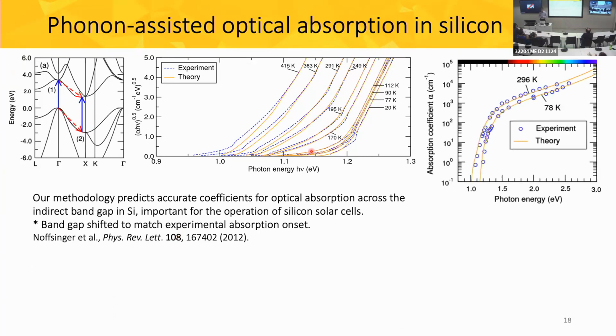But most importantly, we also find how the absorption spectrum varies in the visible range. So that gives us the key quantity, the key result about how silicon absorbs visible photons, which was for the first time we're able to obtain this quantity. So the data you see here from experiment is 50 years old, and we're able to come with theory and